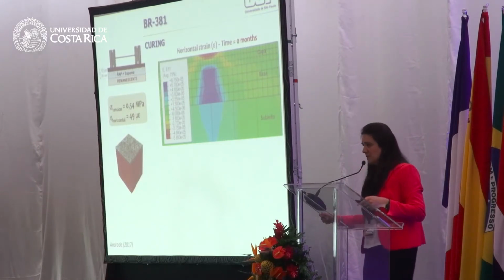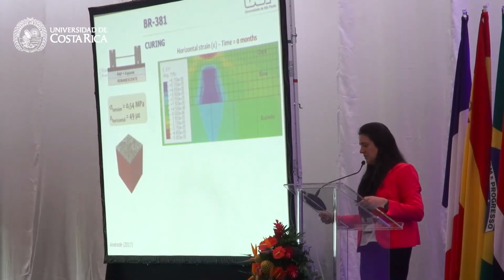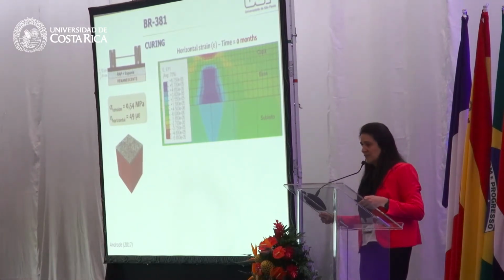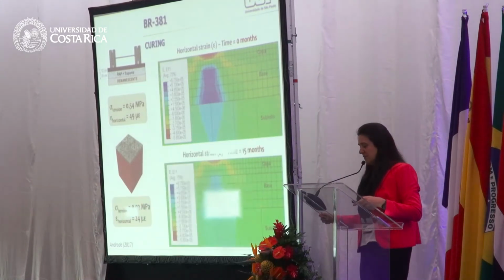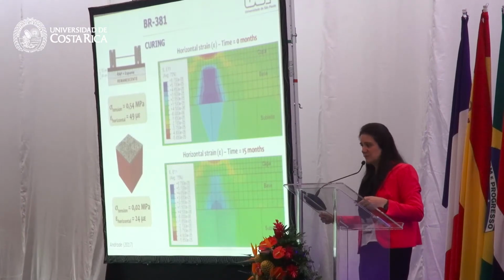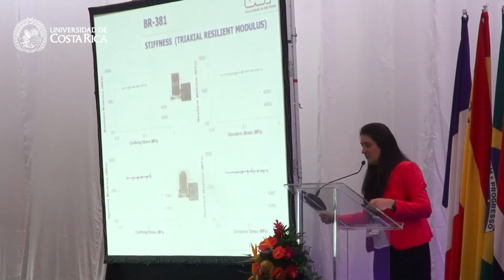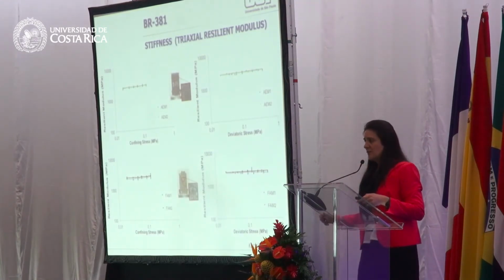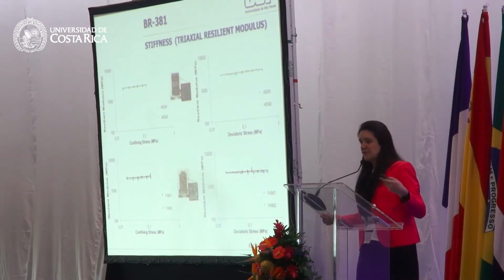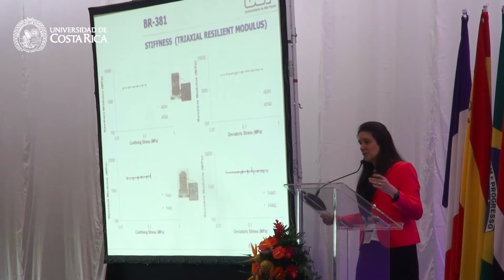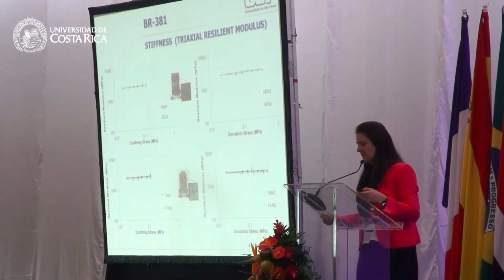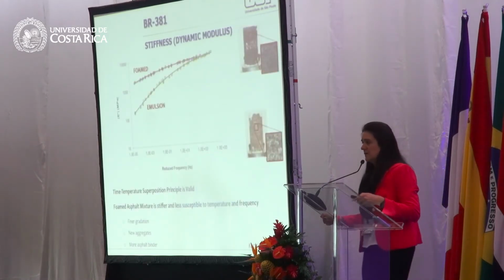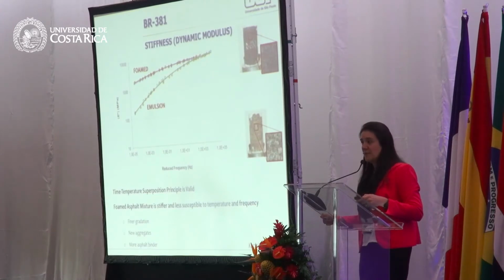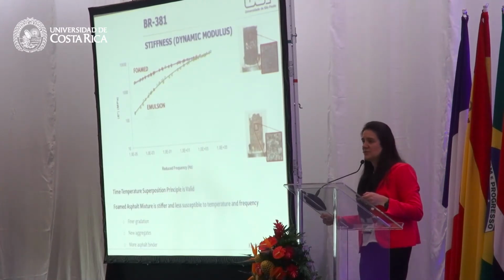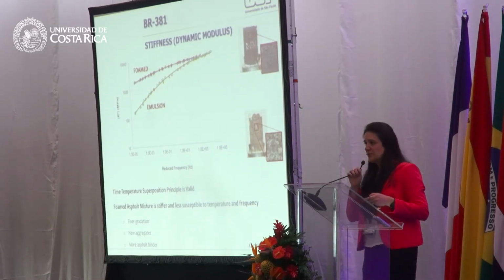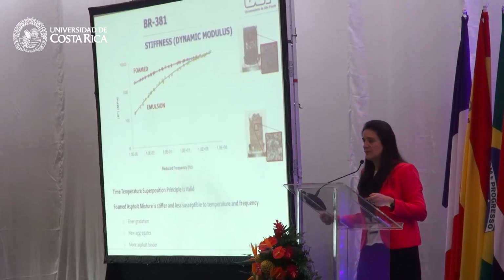Here's some simulation considering everything elastic. It's important to consider. If you check the stresses and strain at the bottom of your HMA layer, you see that after 15 months, it's going to decrease because of the curing process. We've run some triaxial tests too after curing, and we corroborate that if the material is completely cured, the stress state on them is not that much. We've seen that for both the emulsion and the foamed. We've run the dynamic modulus, and this is important for us too. The time temperature superposition principle that fits for the asphalt mixtures, it works for the cold recycling too.